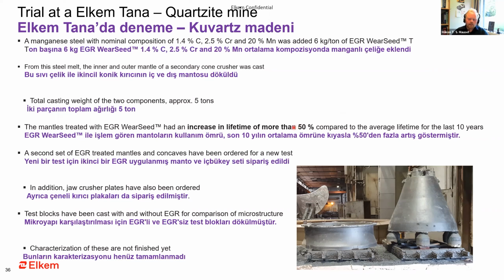And these mantles were put in operation at Tana some time ago, and then they measured it. They have a continuous measurement of all the mantles they put into their cone crusher. And then they saw that these EGR treated mantles had an increase in lifetime of more than 50% compared to the average lifetime for the last 10 years. And actually, when we compared it to the last 3 years, then it was actually 100% increase in lifetime for these mantles. So that is, of course, very good numbers.